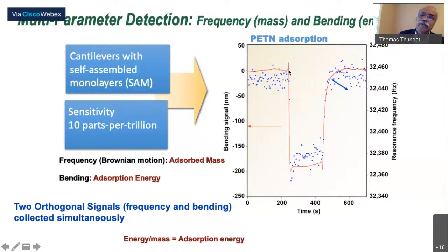So you can see that the cantilever bent. Look only at the red curve, and when you turn it off, it comes back to the equilibrium position. And these blue dots that you're seeing are the resonance frequency of the cantilever, measured every few seconds and averaged over, using a Lorentzian fit. So that basically follows the bending curve almost in a faithful fashion, and the scatter is because of the averaging involved.